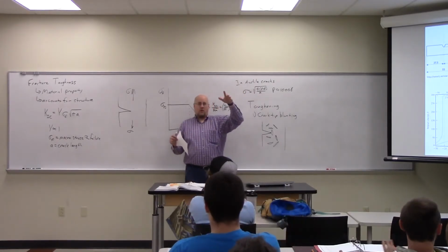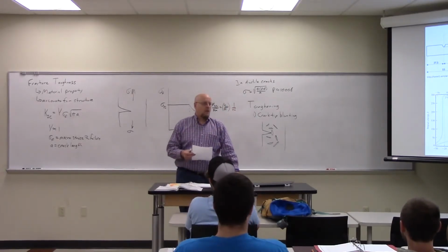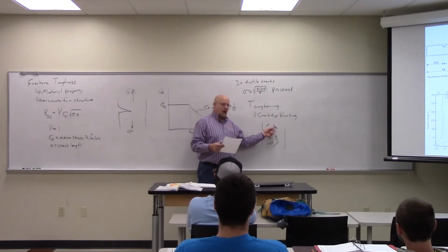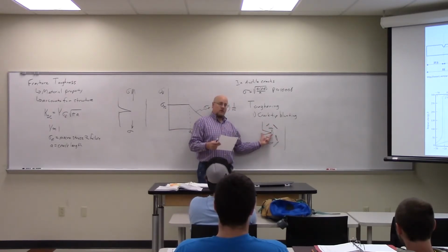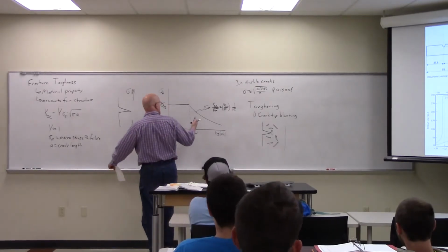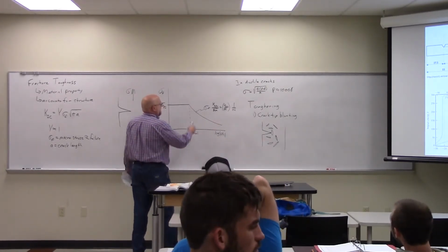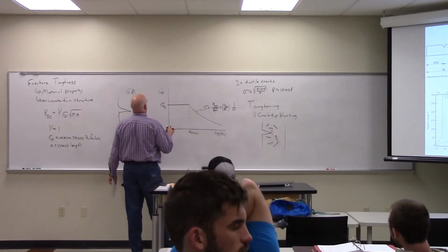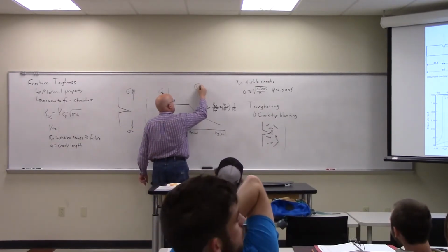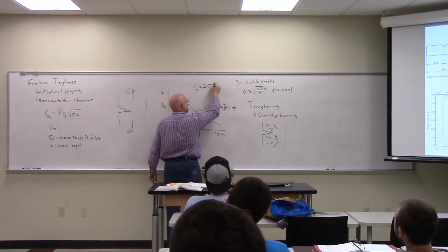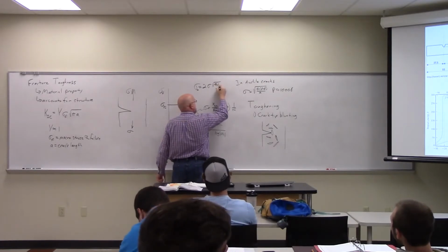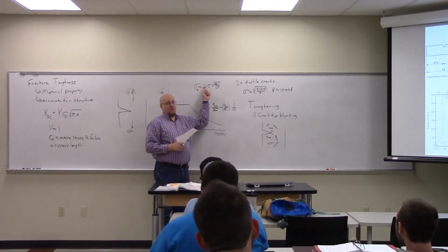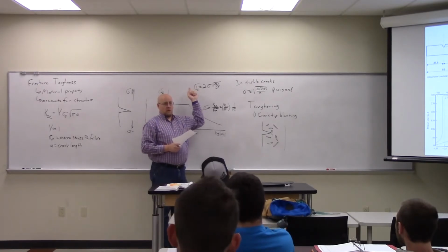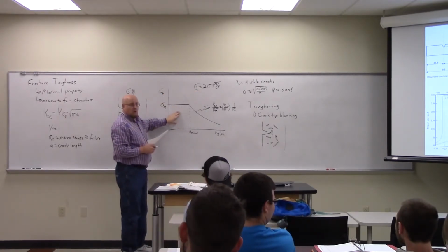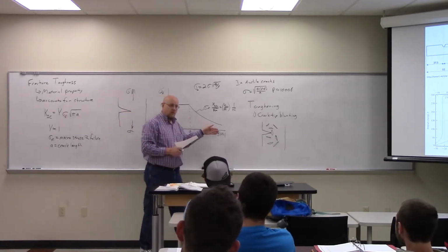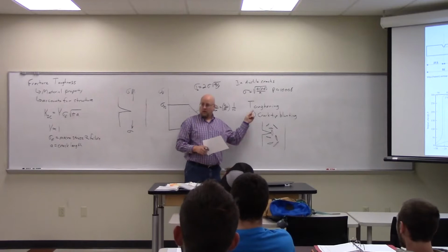So that's one way to toughen the material, is to put these extra, yes? But those micro cracks, if they're shaped like that, yeah, but these micro cracks are much shorter length than this. So if the A is short, oh, I've erased it. Wherever the sigma, I can't even see it in the white erasure mess. Anyway, the sigma max equals 2 sigma square root of A over rho, right? Those have very small A's, so they have very small stress concentrations. Okay, they're small A's, they're down in here. We don't care about those. It's the big ones we want to blunt off. Does that make sense? Okay, so that's one way, blunting.